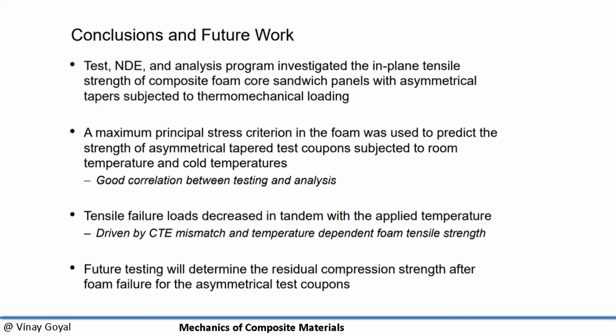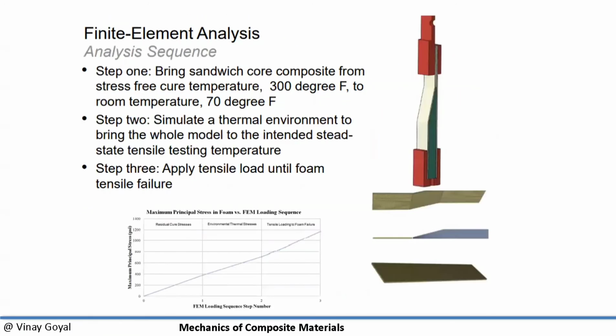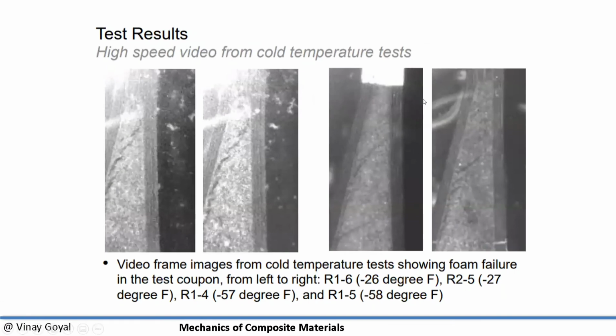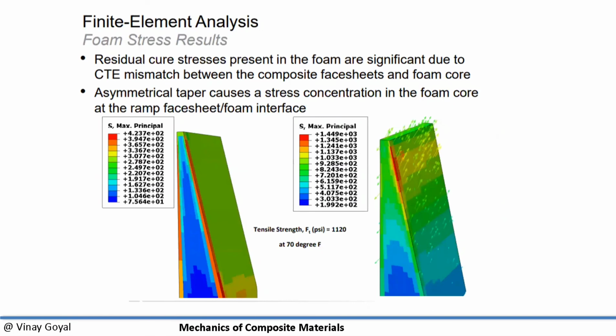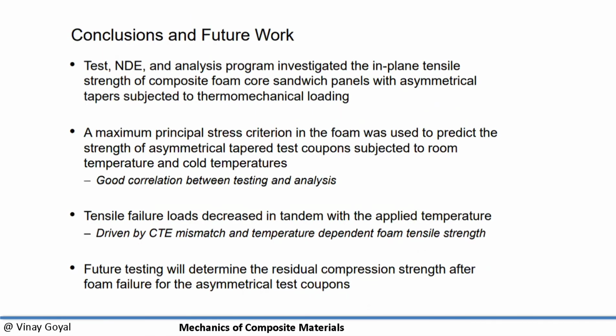The conclusion is that when you use systems that are complicated, like the one I showed, a composite ramp, you have to really consider full test, non destructive evaluation, and analysis methods to investigate why failure occurred and how you can increase its strength if possible. And we also showed how by looking at the different failure modes, in this case, we knew or we found through a lot of research that foam failure was happening. But you can see how high-speed video can help you narrow down the failure mode to one, and you can then examine that one in your final model and gain more confidence in the modeling techniques. So it's important to then gain that analysis and testing correlation because then you can use analysis for other things.